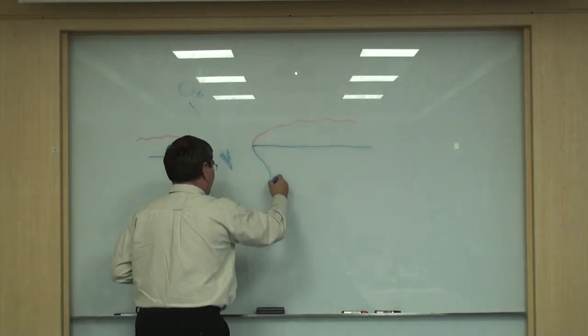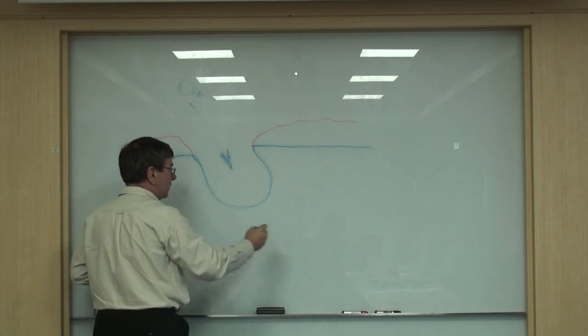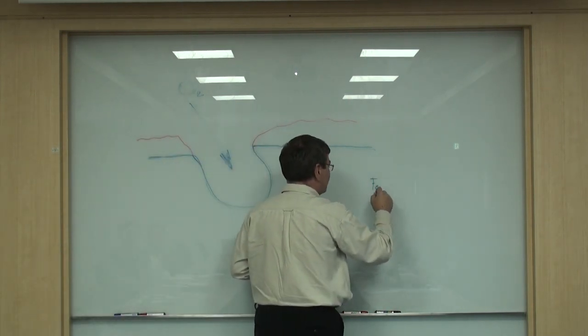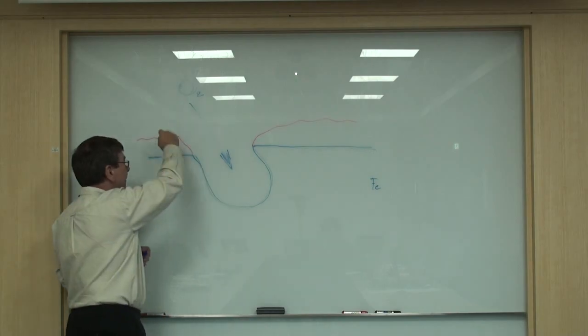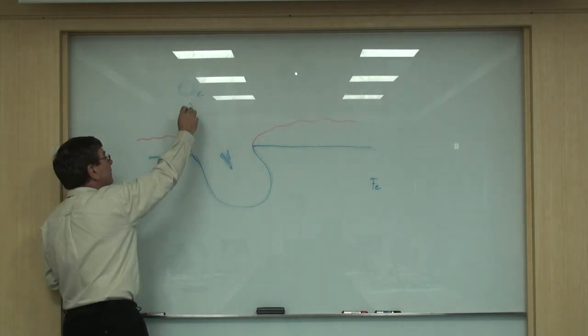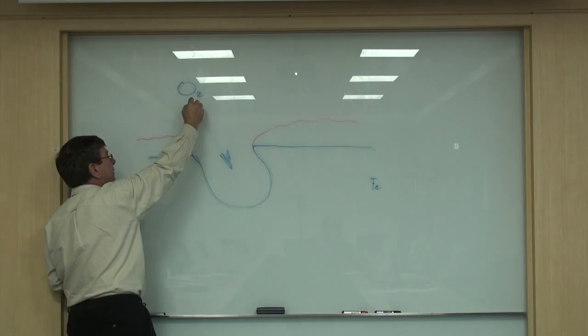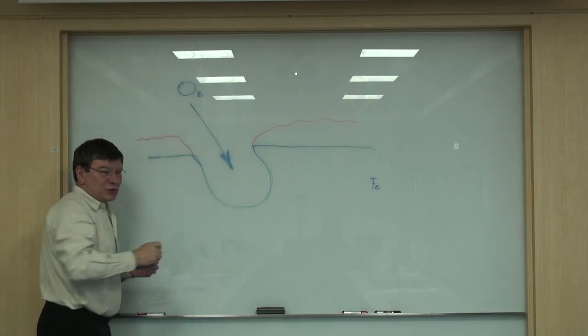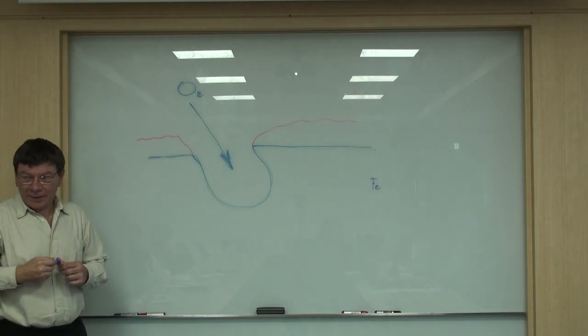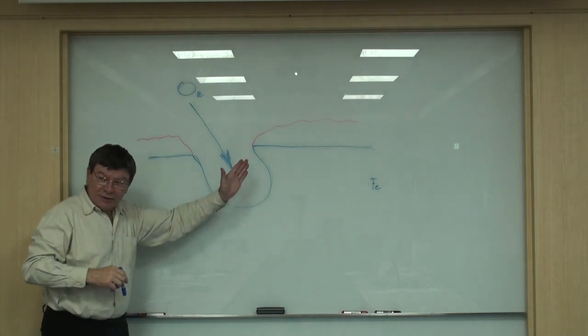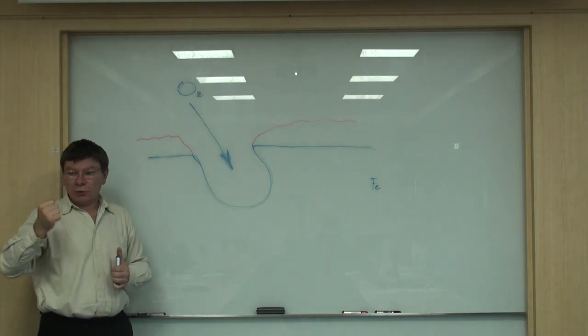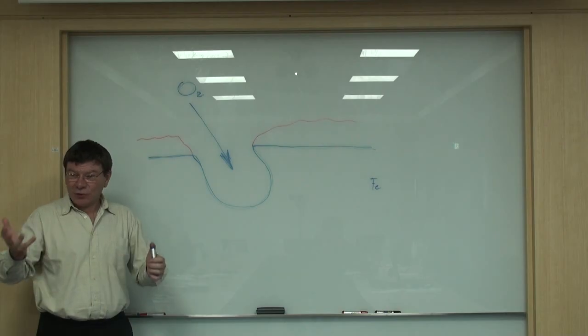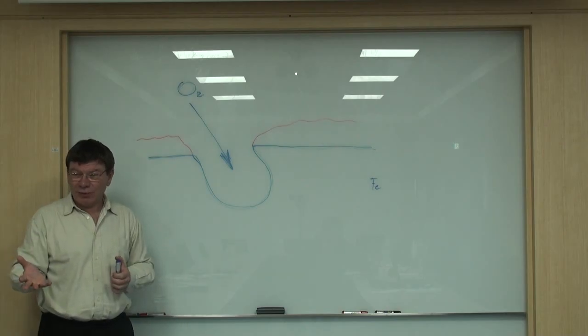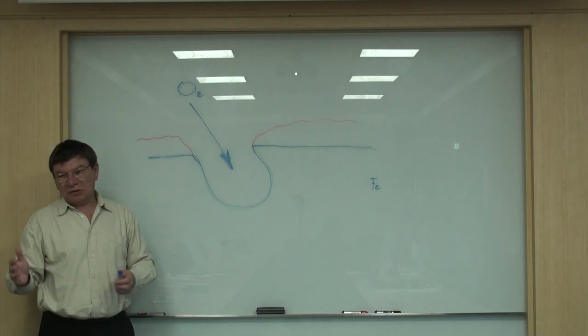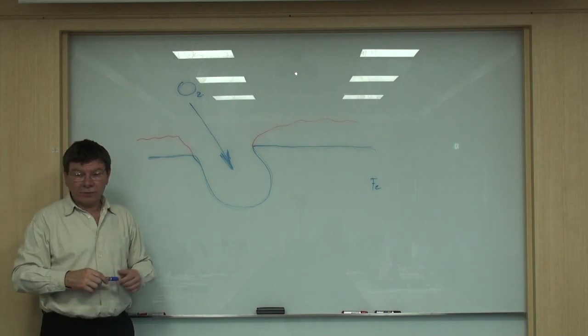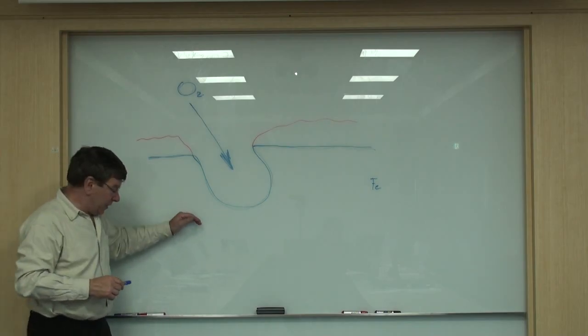Here you have the bath. Yeah? This is the steel. On top you have the slag. And here you have oxygen injection. We suppose supersonic oxygen injection. Yeah? That creates a nice cavity. The consumable pipes. It is also possible to inject oxygen with consumable pipes. But we will see that it's not a very good tool anyway for the bath work. To clean the door, okay.